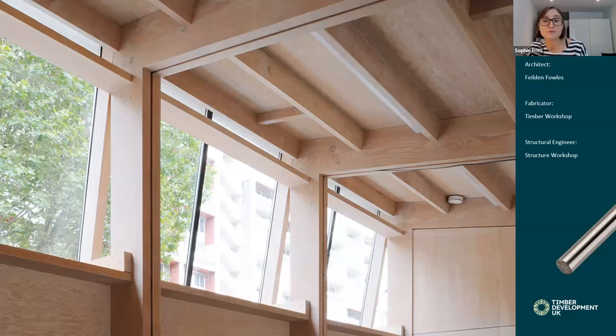So another type of fastener similar to bolts is a smooth steel dowel, but it's just without the head and the nut. This offers an attractive alternative with a slightly reduced capacity. The reduction in capacity is due to the absence of the clamping that you get when you tighten a nut on a bolt, which Andrew will probably touch on a little bit more when he talks about the more technical side of dowel-type fasteners. What's nice about dowels is that you can size them so they're slightly less wide than your timber assembly, and then you can plug them so you can create an invisible connection if that's what you want. This plugged type joint is also good if you have an exposed connection that needs to be designed for fire, because your plug can protect your dowel.